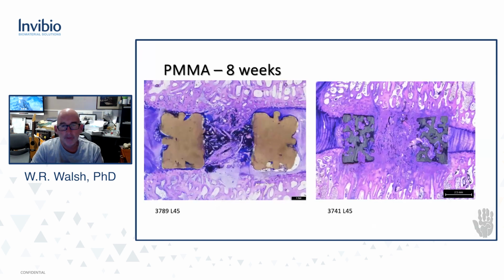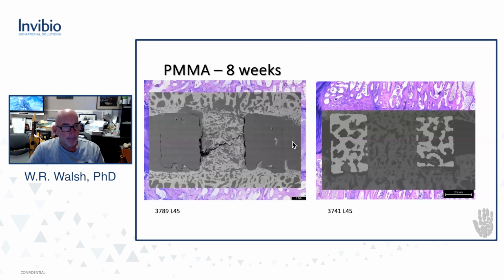And then we go on to histology. So this is serial sectioning of histology in the sagittal plane, PEEK at 8 weeks, titanium at 8 weeks. We can see some integration, a little bit in the end plate there, disappointing, but that's only like a millimeter. But that's what we ended up getting on that case, again, on the end plate.